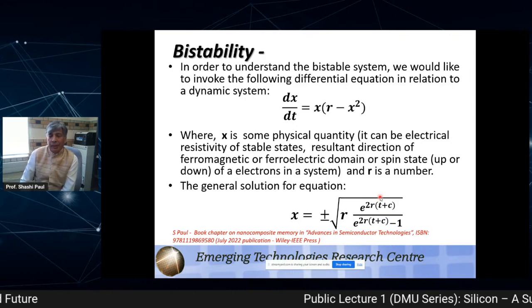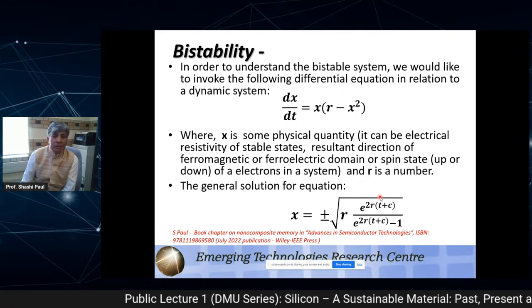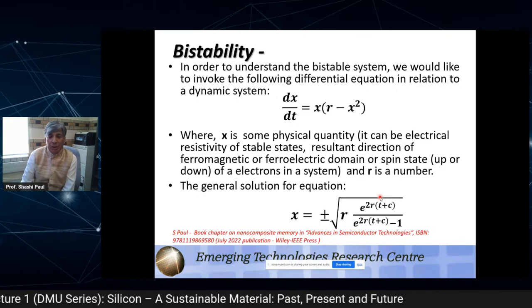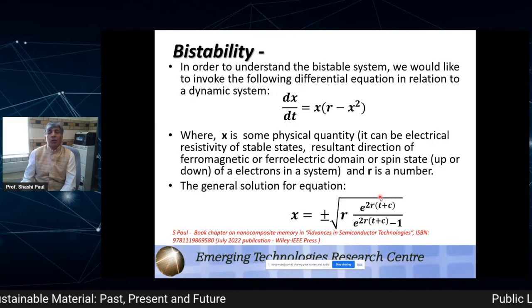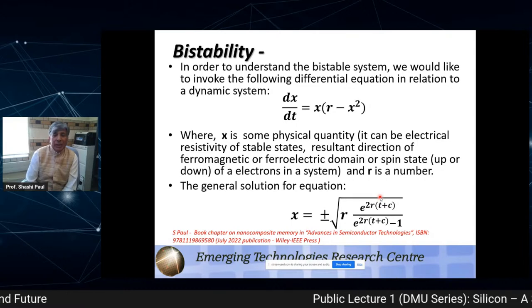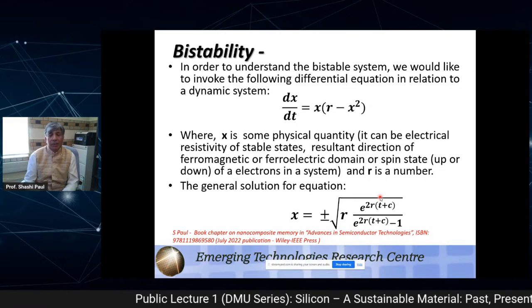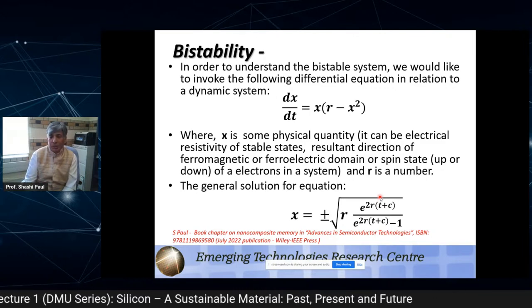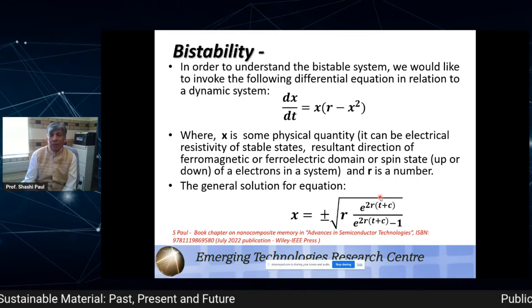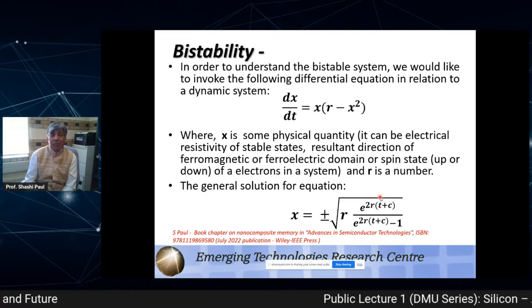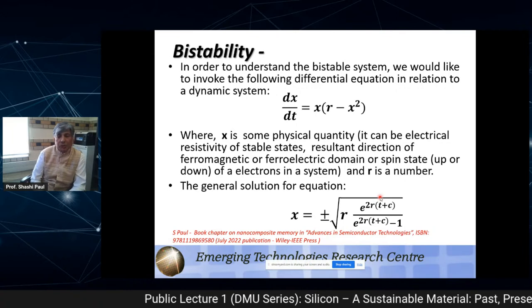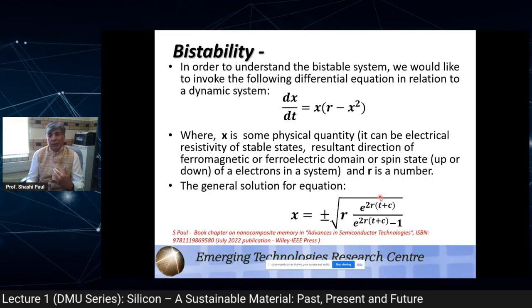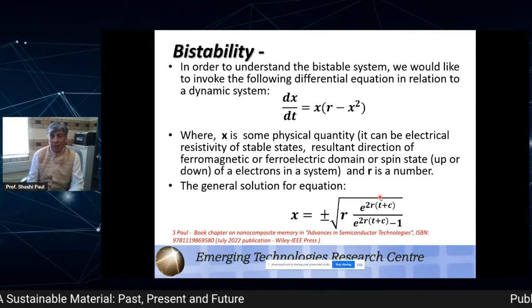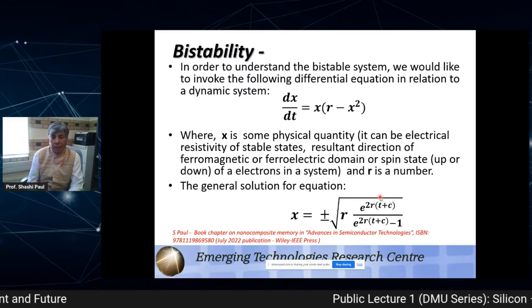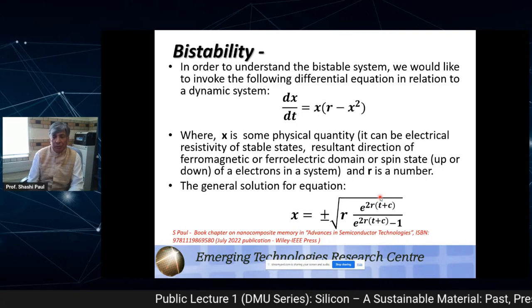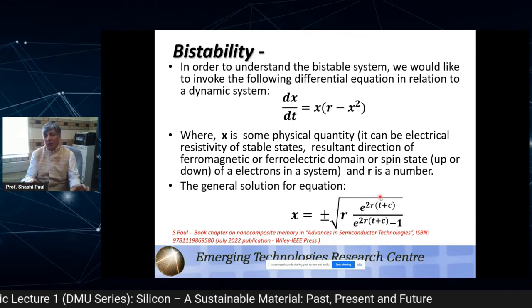Why? At DMU with my colleagues, we have been working for the last nearly 17-18 years hunting for a memory which can store information for a much longer period of time. Because my objective is, can we store information for infinite time? The reason behind it: if you think about your memory stick, the USB stick, it can't retain the data for more than 3-4 years. Even if you don't use it, it will start corrupting or disappearing by itself because of some quantum issues, a quantum tunneling issue. So the idea is to create something which can be retained for a very long period of time. The only gadgets which can store information for 50 or 60 odd years are magnetic tapes, not even your hard drive or anything like that.